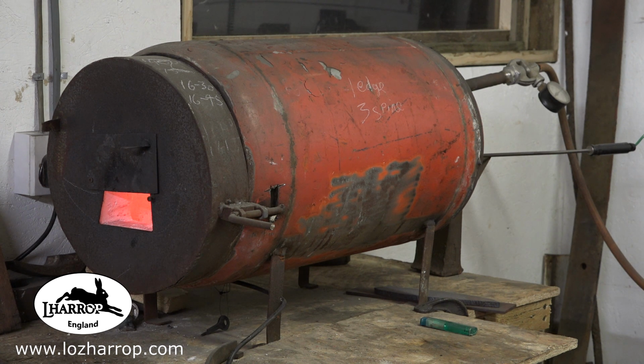Just working off a magnet coming out of a forge isn't the best, because to get the best out of a heat treat on any steel, it does need to soak. You need time for the carbon to move through the iron molecules, and for everything to get distributed, for the grains in the steel to sort of move and mesh together, ready for the final quench.